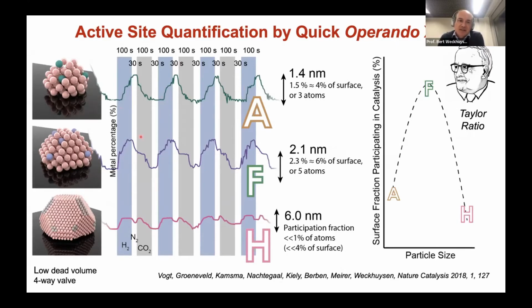What you can notice is that if you plot metal percentage as a function of these pulses, you can see that it changes. When you have hydrogen it is more metallic, and when you have CO2 there is adsorbed CO2 on it, hence the surface has some oxygen at its first surface. Now, this works very well for small nanoparticles. With larger ones, you see that you have some bumpy road here.